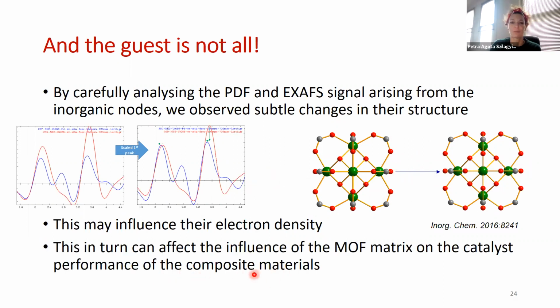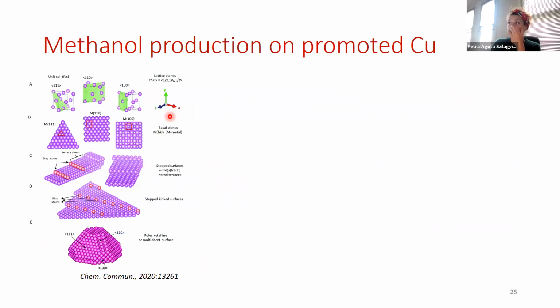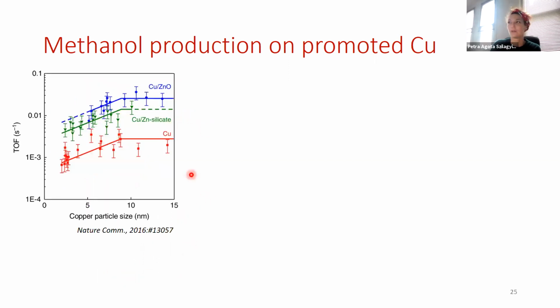And this is the last example I would like to give, because we had found that this may have an impact on the performance of a MOF-based catalyst. This is related to methanol production and promoted copper. I'm very sure that you all are very familiar with that, so I'm not going to go into a lot of detail. I can just tell you in advance that we didn't make much methanol. You would be familiar that, of course, when you use a zinc oxide promoter, the activity is enhanced significantly.